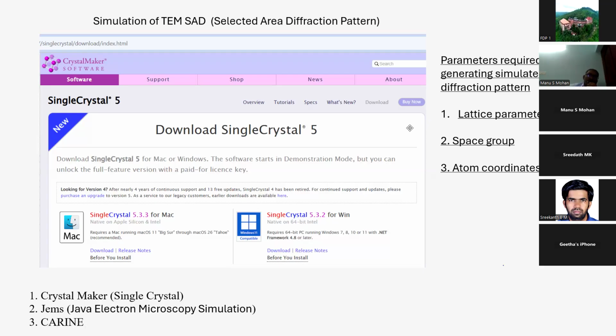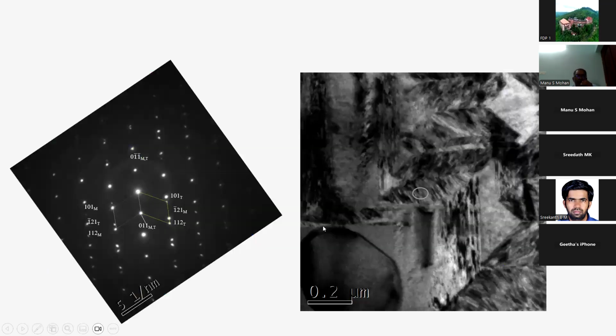So you need to have the knowledge of three things, basically: the lattice parameters, the space group, and the atomic coordinates. Only when you have all these three can you produce the diffraction pattern. Again, this is from my thesis work. So this is a TEM bright field micrograph shown here, and then you have a diffraction pattern.